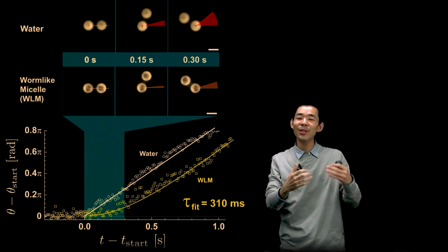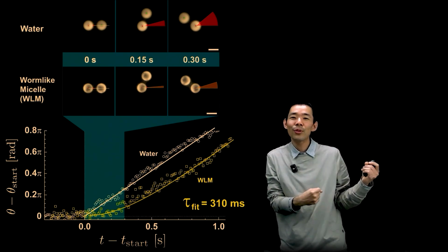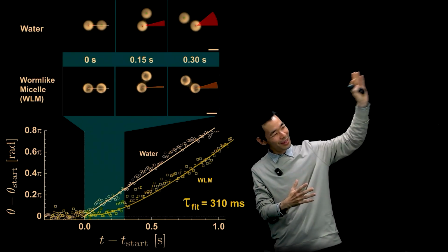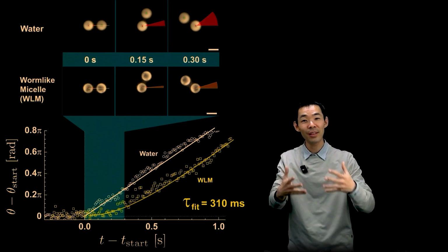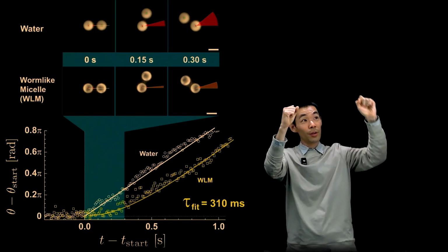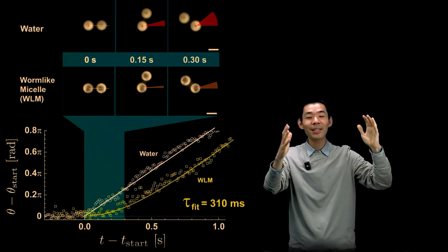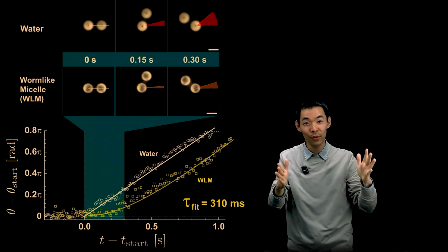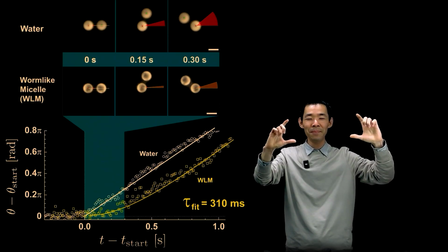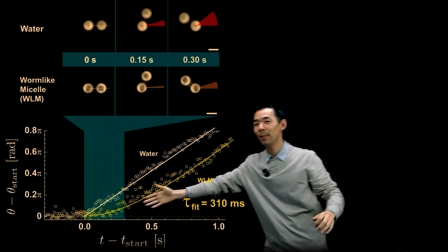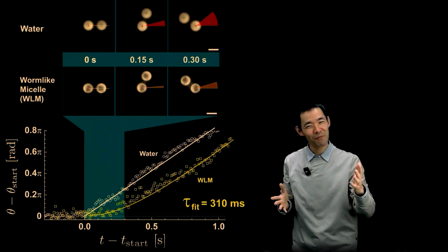That's because there's this memory effect: it takes some time for the center particle to respond to the particle driven very far away. Now, Sachet developed a theory for the two-particle mobility resistance hybrid coupled problem in the case of a linear Maxwell fluid, and used that linear Maxwell fluid constitutive equation, did the exact same problem, and obtained this yellow solid curve. And it fits very nicely.